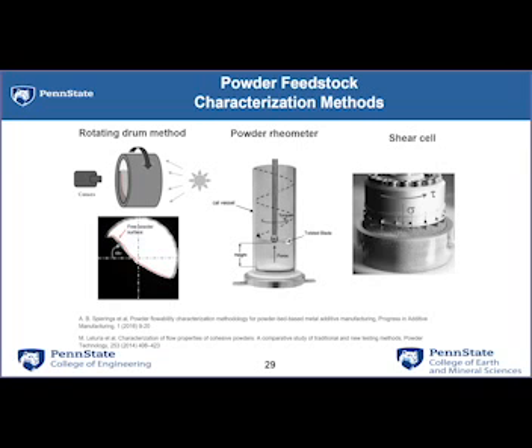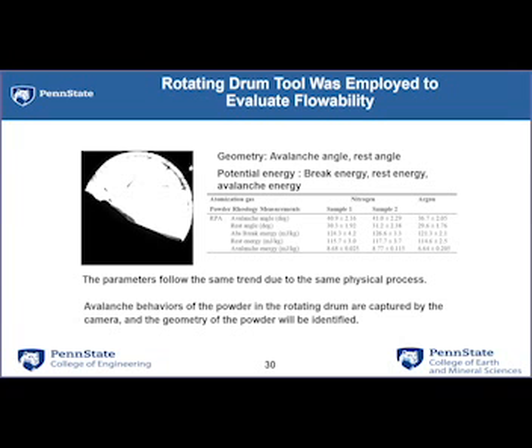We have capabilities here at Penn State for different types of techniques. They go from as simple as a rotating drum, which is really just an image analysis system that rotates a powder mass with a camera and measures avalanche angle, to powder rheometers, where blades and torque meters are used to measure the torque required to move a blade through a powder, or a shear cell, where we can measure permeability and other packing and void space type techniques. And we often integrate this with the computed tomography, or X-ray CAT scan, capabilities that we have, to understand how they all fit together and give us a lot more insight into what's going on with the powders.